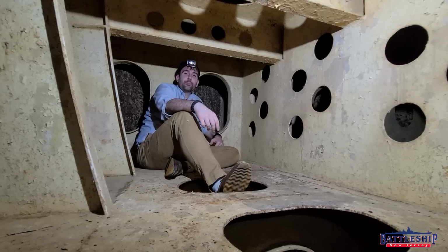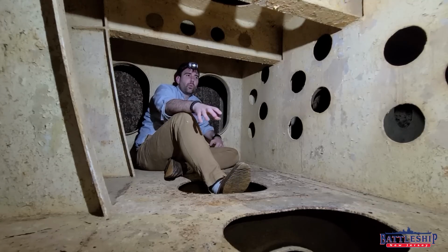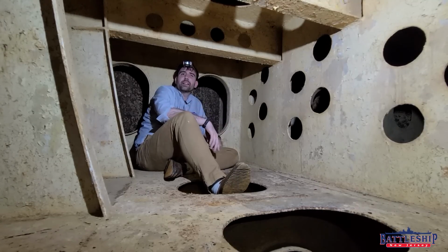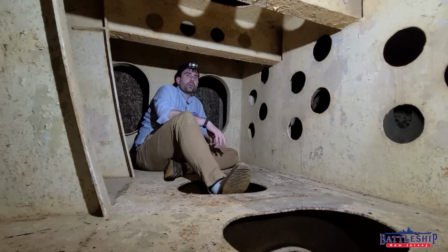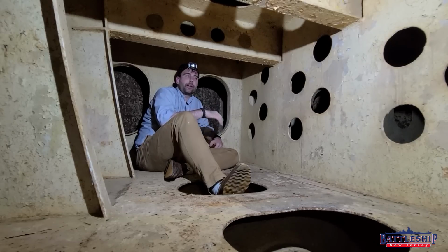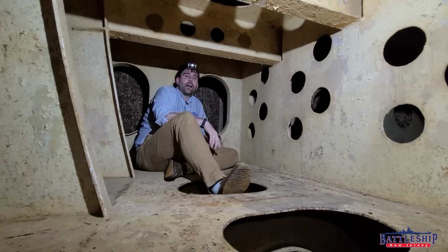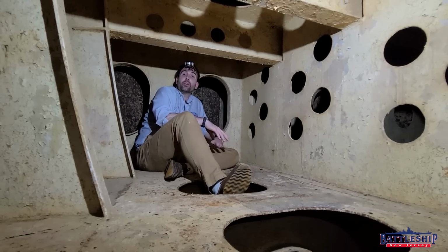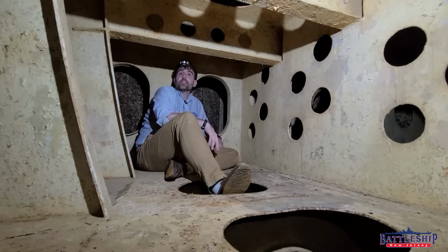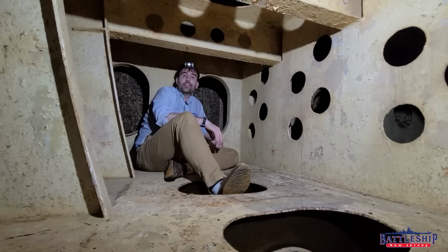When we go into Drydock, because there isn't any leaking here on the inside or any significant corrosion, we're not going to touch the inside of the ship. We can always come down here and spray it when we're pier side. We're going to specifically look at the outside of the ship, right here at the bow, around the peak tank, the wind and water line, and here at the extreme prow of the ship. We're going to blast it to white metal, and we're going to put a really high build coating or system of coatings on this known to be thin steel, just so that we can avoid some of the problems that we've seen on other ships.